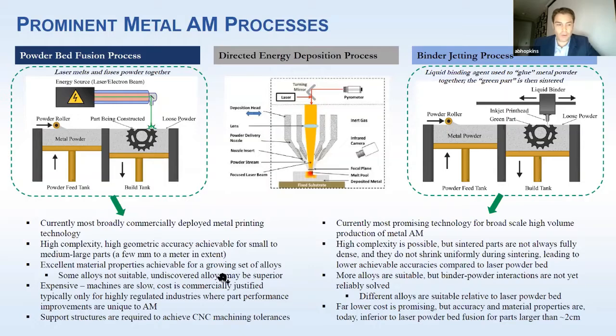It works very well for easily weldable alloys. So eutectic alloys for aluminum like AlSi10Mg or A357, 356, that's an aluminum silicon alloy. It doesn't work very well, I'll give an example later, although there's some good work on this, for, for example, aluminum 6061. 6061 is the most commonly machined alloy in the world by tonnage. I think together all tonnage of machined 6061 exceeds all tonnage of all other materials in CNC machining. So it's an important one, but it's non-eutectic. It's aluminum with a bit of copper. It has phase separation problems as it hardens, as it solidifies. I'll touch on that again later. So it works for some alloys, it doesn't for others. You could make it work for these complicated alloys with careful approach, engineering and physics. And the machines are expensive, so problems.